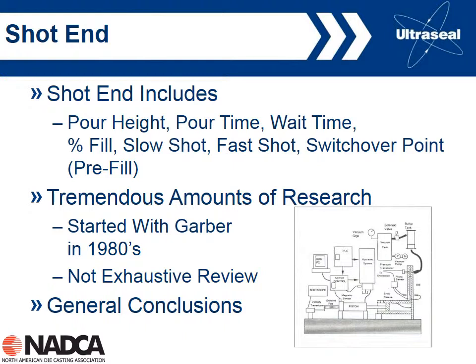So let's talk a little bit about some of the shot parameters in the shot end. We've talked a little bit about pressure, but there are other parameters that we can play with. This is really more to do with cold chamber. We'll talk a little bit about hot chamber later. In terms of parameters, we have pour height, pour time, and wait time. But the ones shown in red are really the more important ones: percent fill, the slow shot velocity, the fast shot velocity, and the switchover point, i.e., the amount of pre-fill. People have looked at these parameters for a long time. Probably the most famous is Garber's work from the 1980s, but it goes back even further than that, to the 1960s or so.